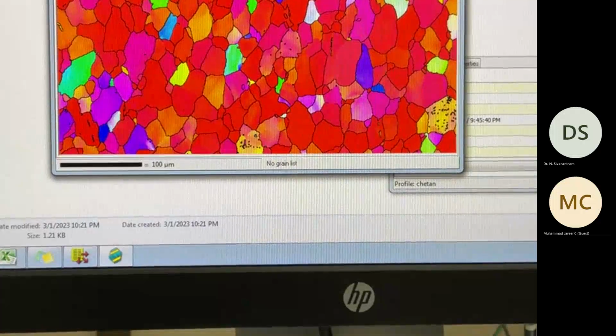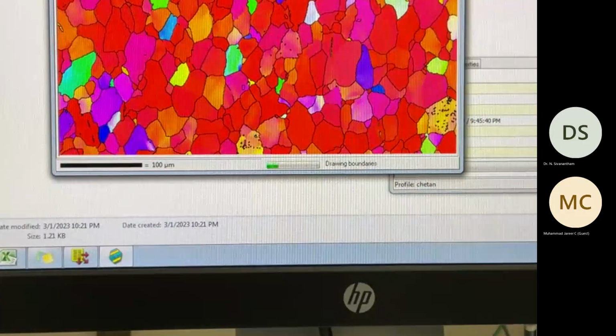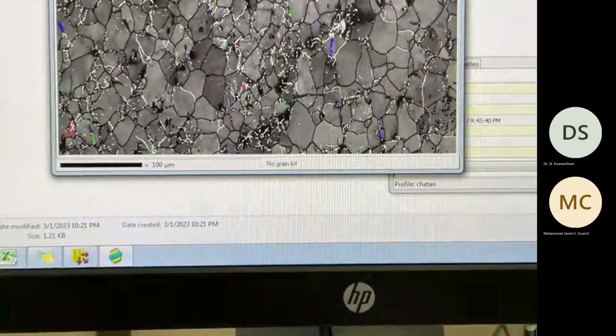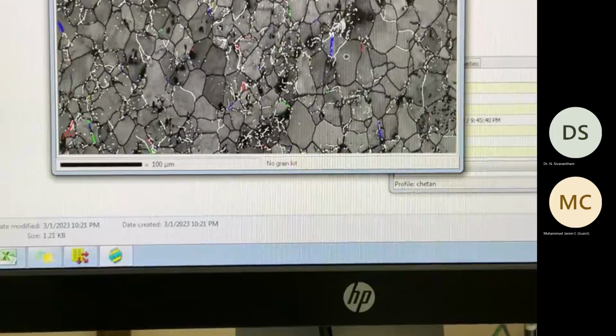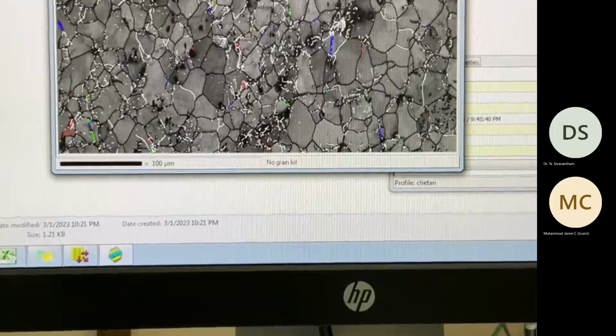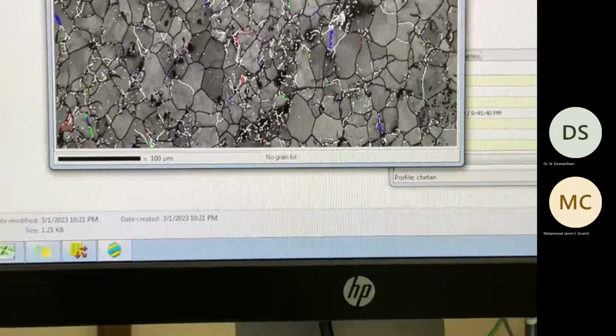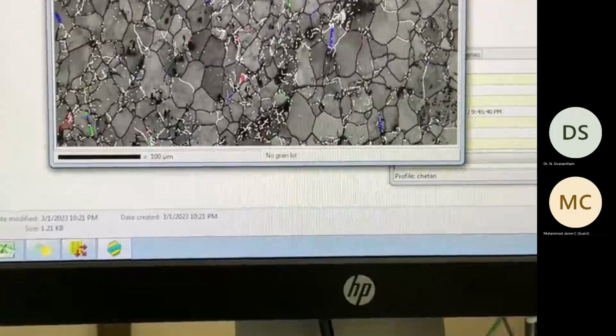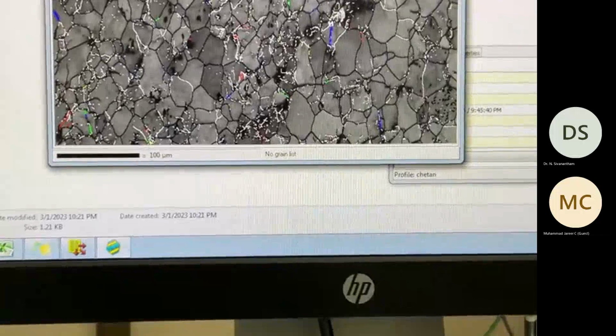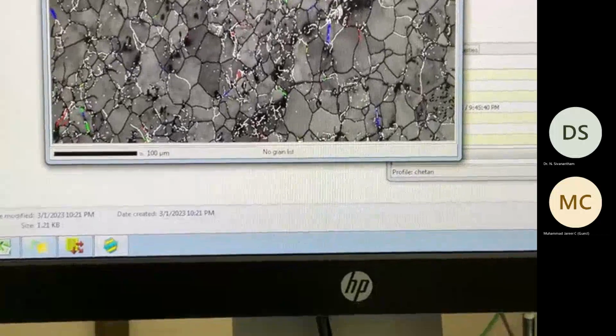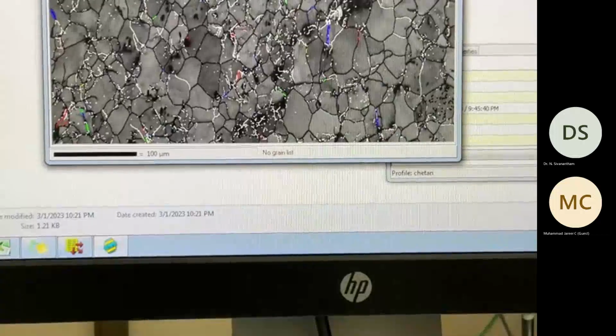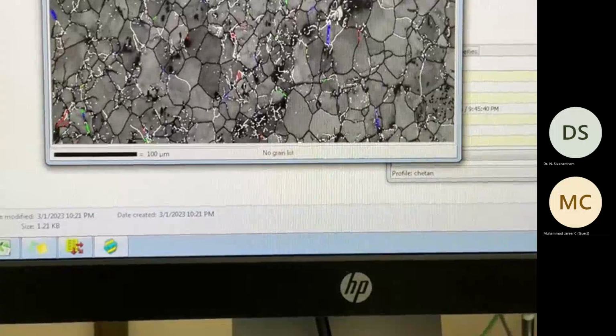You can even get the grain boundaries or the subgrain boundaries, and then the band contrast map and how it is present. If any twins are present, you can see them. If you want, we can see the rolled sample, where it will have a lot of twins. This is a recrystallized sample, and you can see the grains are more than 150 microns.